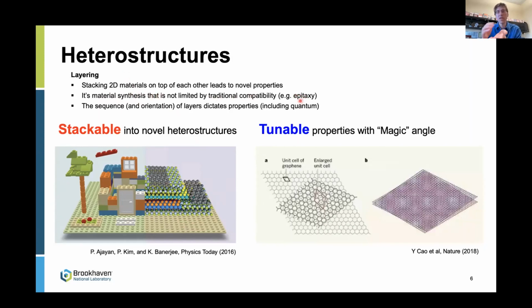So if you think of the normal way you might make a multi-layered film, let's say you have some gas molecules in the vapor phase and they deposit on a surface. So you introduce one set of molecules, they deposit on a surface and form some layer of atoms. And then you introduce a different set of molecules into the vapor phase and they deposit on the surface and form a second layer. But you don't really get to choose how those layers go on top of each other, right? Energy minimization, equilibrium chemistry is going to dictate what structure forms in that bilayer.